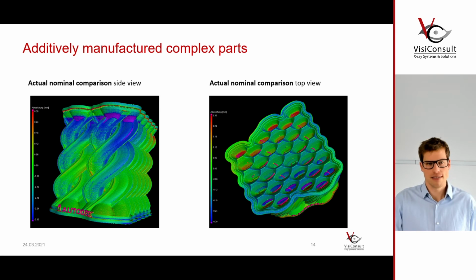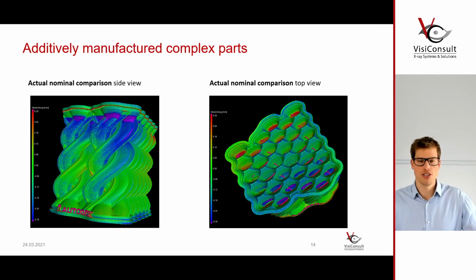And the most impressive area, I would say, is geometric deviation, because this is where additive manufacturing, for several reasons, may it be residual stress, temperature gradients, fluctuations in the laser intensity, gravity, build design, there are many reasons why the geometric deviation of a part can change from what it should be. So what you can do with computer tomography scans is that you can do actual nominal comparison. That means you compare the actual shape and geometry of the part towards the CAD and to what was intended.